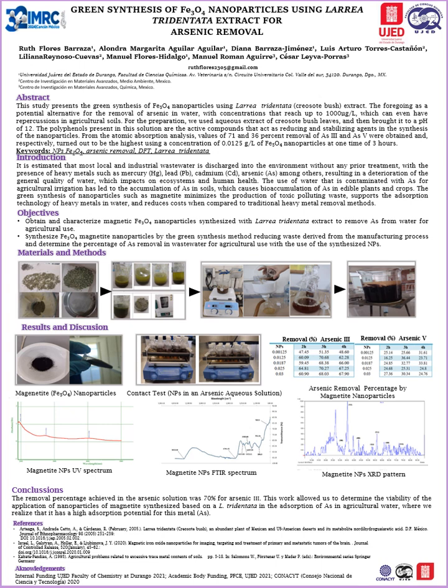synthesis of the nanoparticles. From the atomic absorption analysis, values of 71 and 36% removal of arsenic-3 and arsenic-5 were obtained, respectively, and turned out to be the highest using a concentration of 0.0125 grams per liter of magnetite nanoparticles at a time of 3 hours.